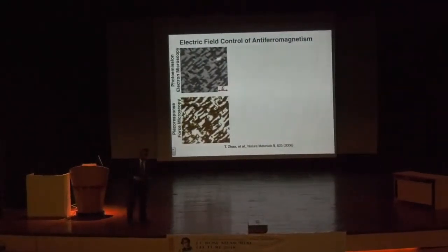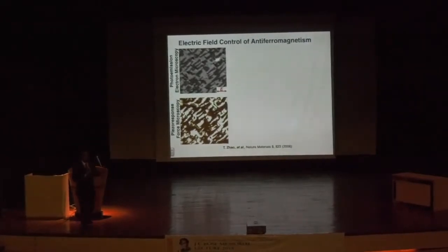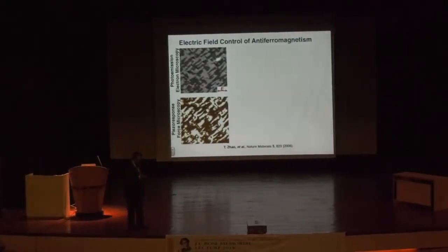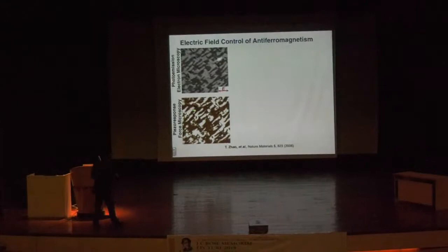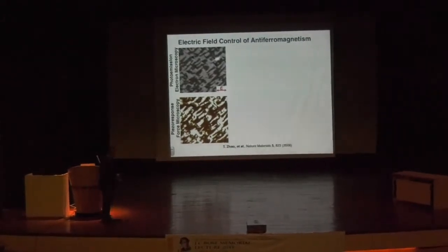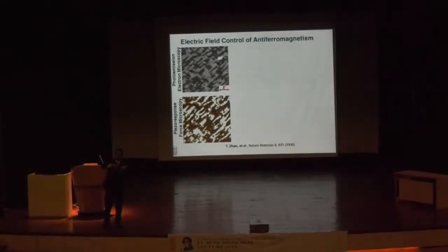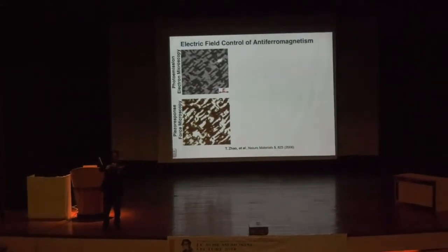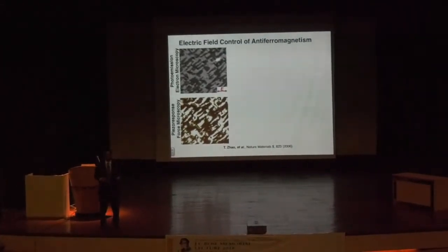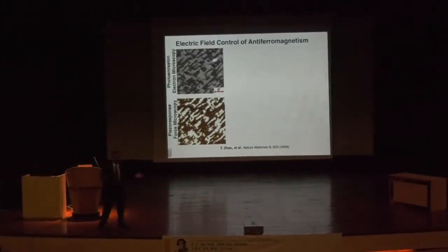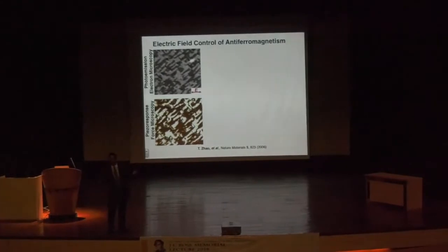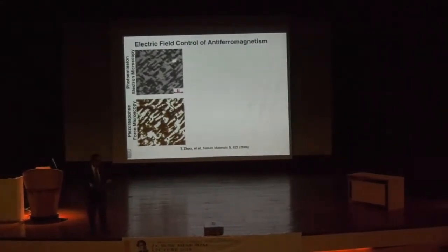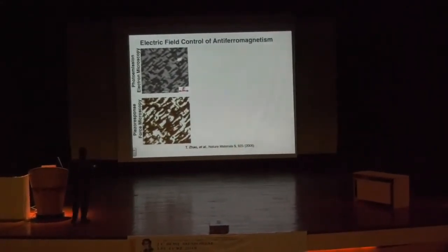And so the first experiment, this is now about 12, 13 years ago, was where we did a combination of two different experiments. We looked at the ferroelectric structure using piezo force microscopy, simply coming to the surface, and you put an AC signal on the surface, and the crystal would do the same. It'll be in resonance with the amplitude of the cantilever, and so you can map out the piezoelectric response with a resolution of about 20, 30 nanometers. Okay. That's what this is, and this is bismuth ferrite.